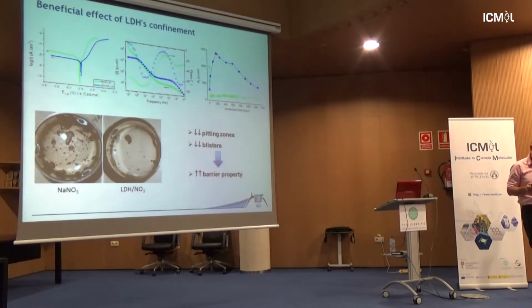So first of all, to get a big picture, nitrate has been identified as a corrosion inhibitor in the past by a Japanese company. If you put sodium nitrate directly into the solution in contact with the aluminum surface, it's not good. It's reacting, it's not preventing corrosion at all. But if you put nitrate in between the LDH layers and it is released slowly, acting as a corrosion inhibitor, it is much better, and you avoid the blister. So you have some barrier properties when you use the LDH itself, and you can see that there is a decrease here of intensity. That's a Tafel curve. That's the way you measure, in fact, the efficiency of your corrosion inhibition. You can work with that Tafel curve.